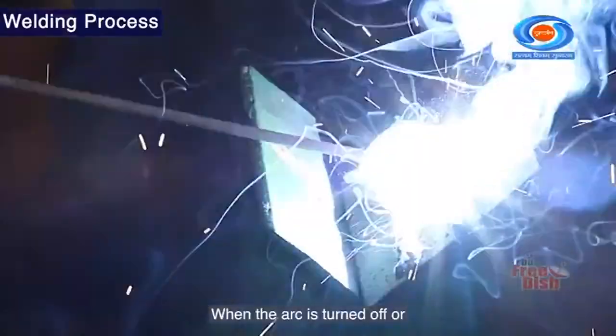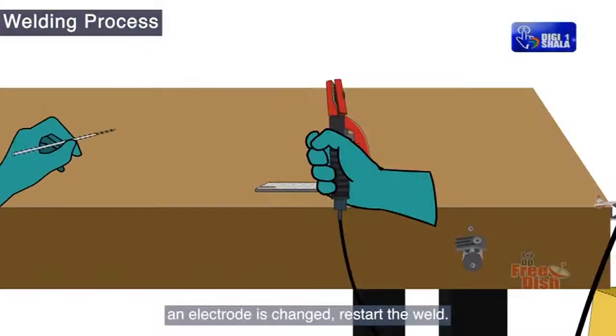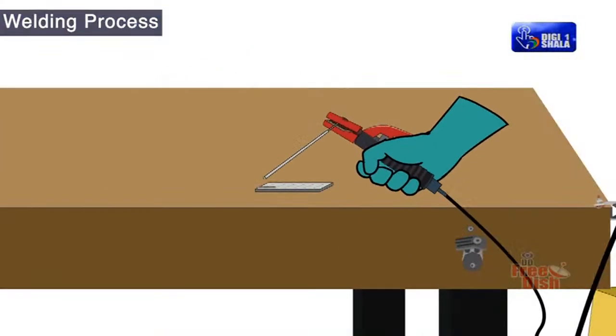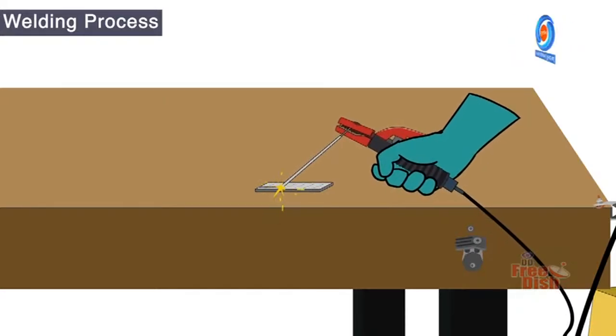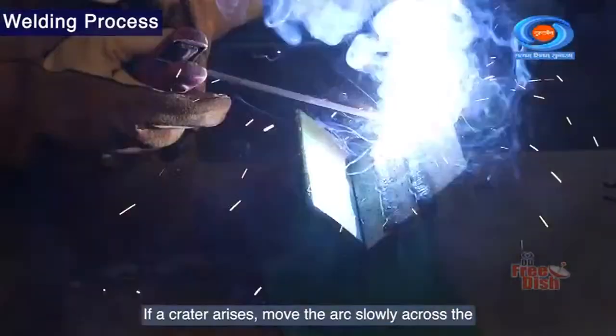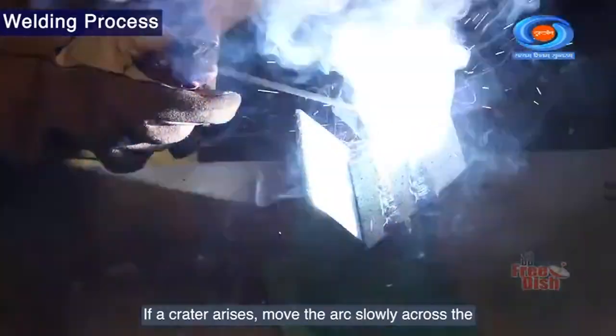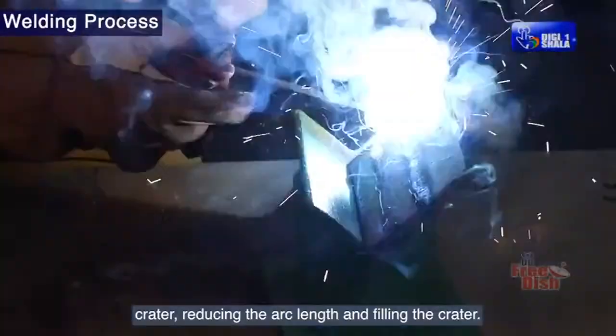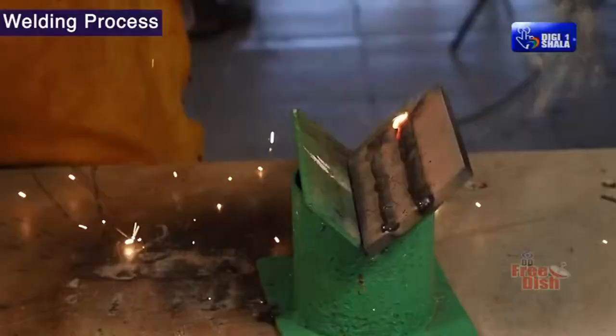When the arc is turned off or an electrode is changed, restart the weld. If a crater arises, move the arc slowly across the crater, reducing the arc length and filling the crater.